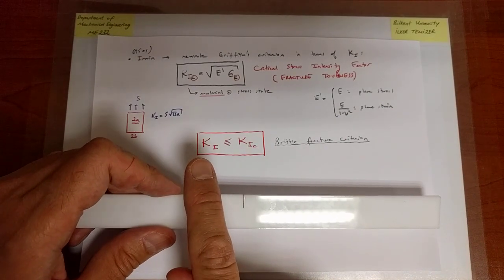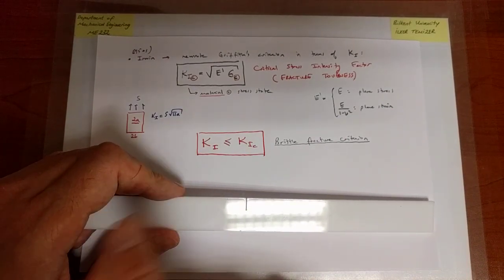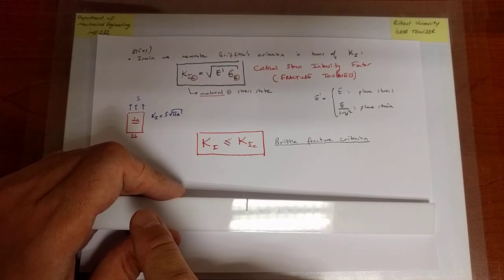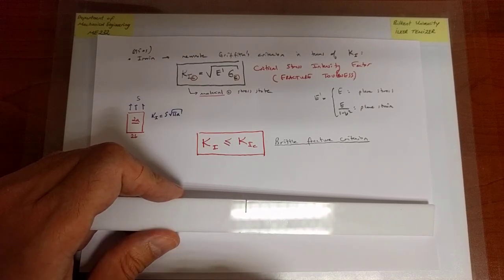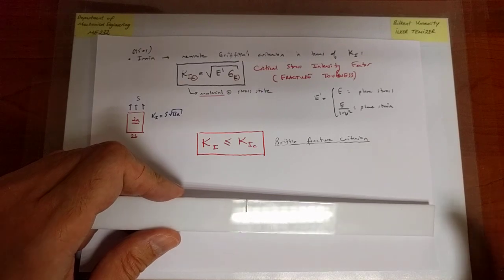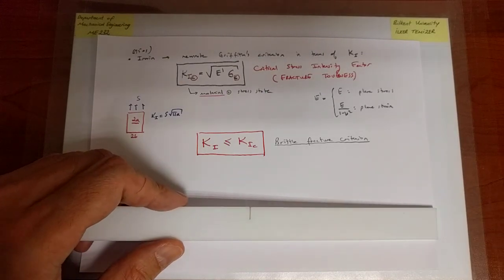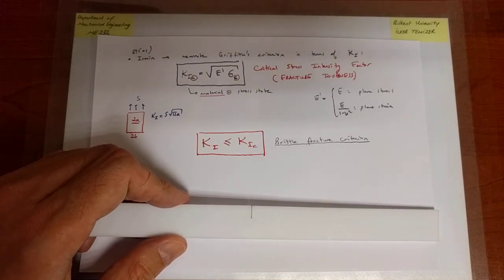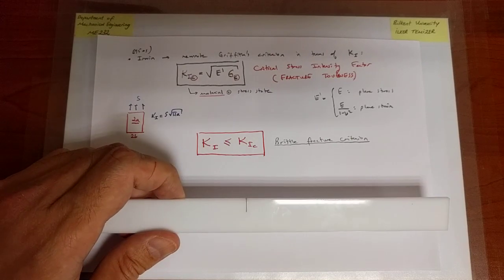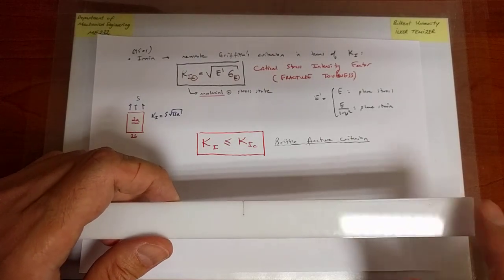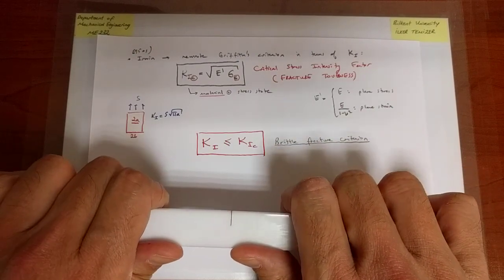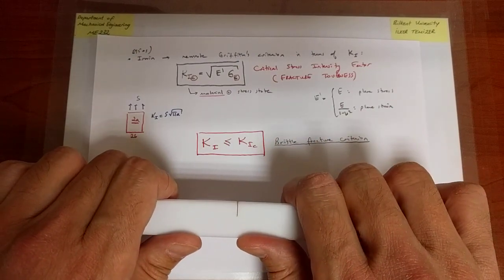Similarly, the fact that surfaces slide with respect to each other doesn't necessarily have to be induced by bending. Actually, it turns out that shear forces that are more natural to torque type loading can also induce mode 2, in other words, sliding type failure fracture. So we're going to discuss those more. But presently, I have an opening mode that is going to be induced by bending.